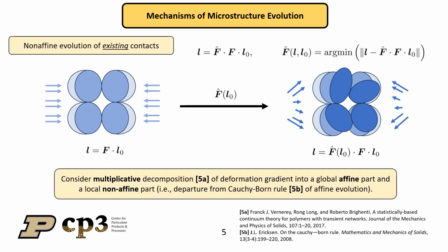We now discuss the different mechanisms of microstructure evolution. One key mechanism that is important to granular systems is the non-affine evolution of existing contacts. And what I mean by this is that in addition to the deformation induced by the global deformation gradient, there are also internal degrees of freedom associated with the microstructure evolution, causing internal rotations as well as other local deformation gradients that can then result in different deformation fields experienced by each grain pair.